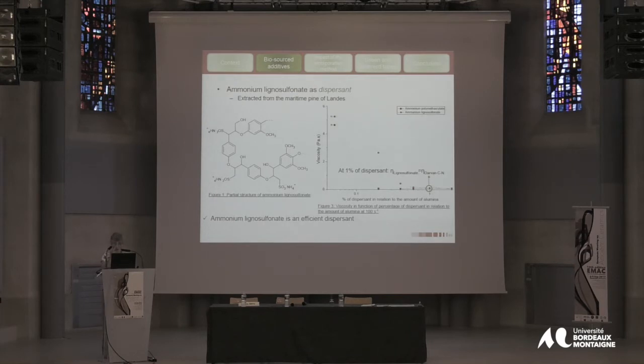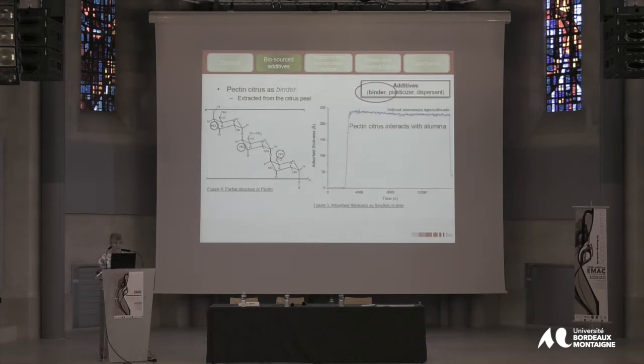Another parameter which we measure when we want to check that an additive is efficient as a dispersant is to measure the viscosity as a function of the amount of dispersant. And for tape casting, what we want is to have the viscosity as low as possible. Again, if we put 1%, which is a minute quantity of this additive in the suspension, we obtain a viscosity which is very similar to what we obtain with the Darvan. So ammonium lignosulfonate, for us, it's a good dispersant for alumina.